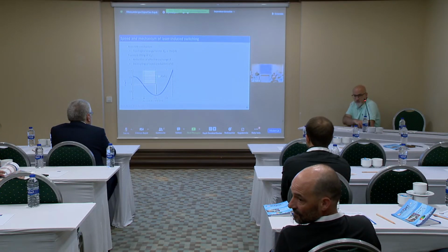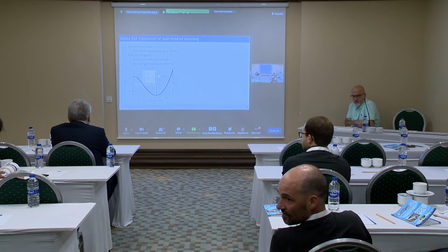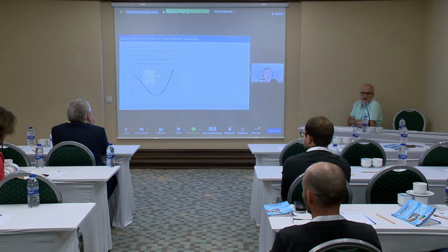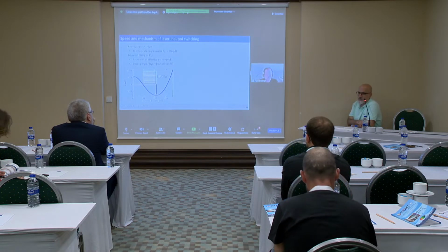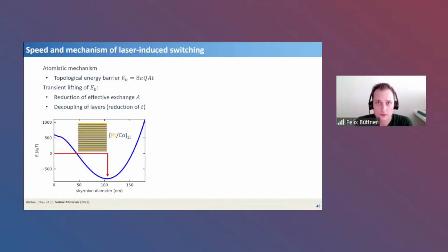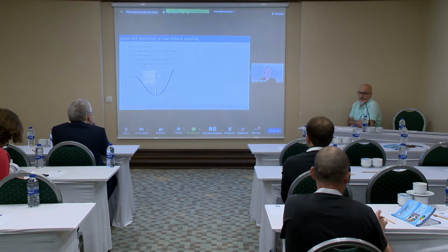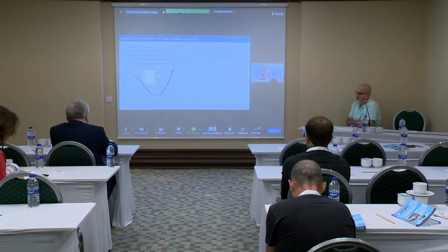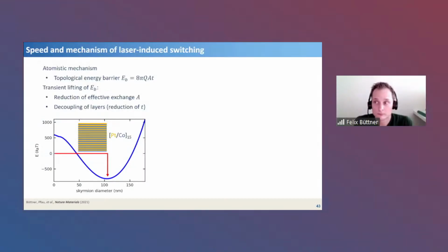Yes. Any more questions? Well, maybe just one comment: in principle, even though they are symmetric, there will be net zero DMI, but I think in a realistic system there are always defects and impurities, so they don't quite exactly cancel out. So there could be some. No, that's true, but probably the DMI would be small. That's right. And the resulting textures are blob type. At equilibrium, they are not Néel skyrmions but blob skyrmions, meaning that the DMI contribution to the chirality is relatively small. Yes.